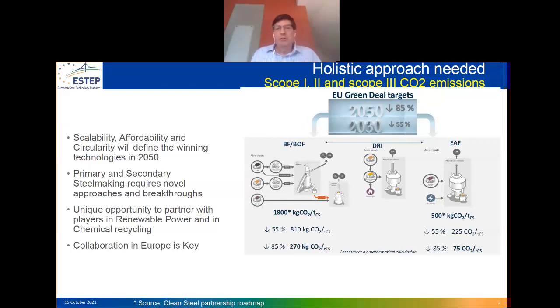And if you go, the middle is the direct reduction, and the right one, the scrap electric arc furnace, we can see that today the starting point, so to speak, for the scrap electric arc furnace route is significantly lower with 500 kilograms CO2 emissions. However, if the primary steel making does its job, and there is no reason to be not confident about this, then the level of today's scrap electric arc furnace is challenged, because then it's double. So there also is the challenge existing to reduce the CO2 emissions.